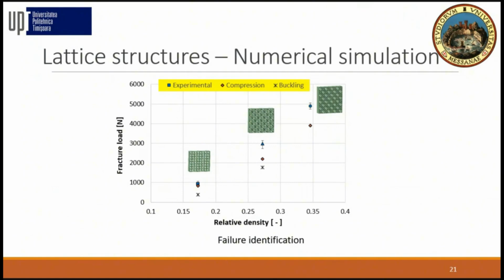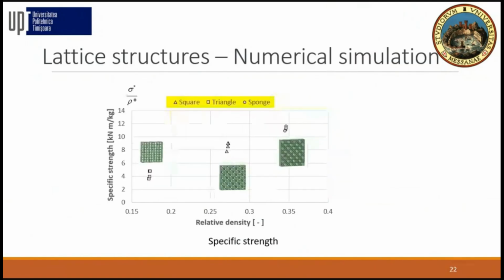We also try to see the specific strength, which is the strength of the structure divided by the density of the structure, and we relate this to the relative density of the foam. So it is the density of the structure divided by the density of the solid material. For this, we build some blocks and we determine the density. We measure them and we weigh them. And this was, let's say, the density of the solid material.